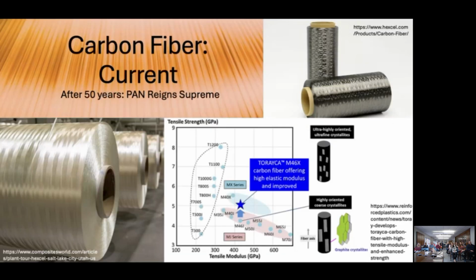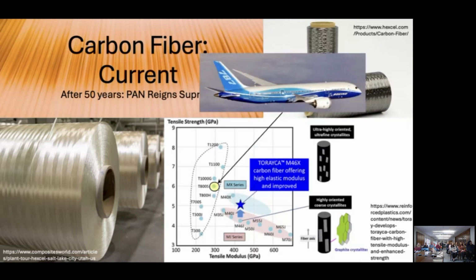So that means after 50 years since 1971, the PAN-based carbon fiber, I would say, still reigns supreme by far. Something like 90% of the market is PAN-based carbon fiber, and I think generously 10% is pitch-based. And as I mentioned, all this stemming from the high toughness of the PAN-based carbon fibers for primary aerospace, which has really propelled it in the recent decades.